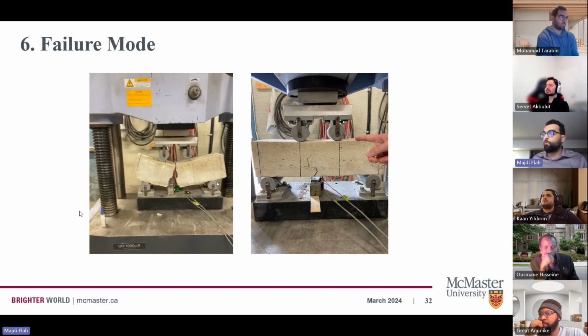So here we are comparing the modes of failure between the normal strength concrete and the UHPC. For normal strength concrete, it's a brittle failure, a purely flexural crack in the middle. When we talk about the UHPC, we started having some cracks in the UHPC and the UHPC thickness. And then I didn't see any problems with the interfacial transition zone. I didn't see any issues with it. I didn't see any debonding. So it looks like we did a very good job when we were preparing the specimens by providing 10 millimeter roughness randomly with that tool we got in the lab.